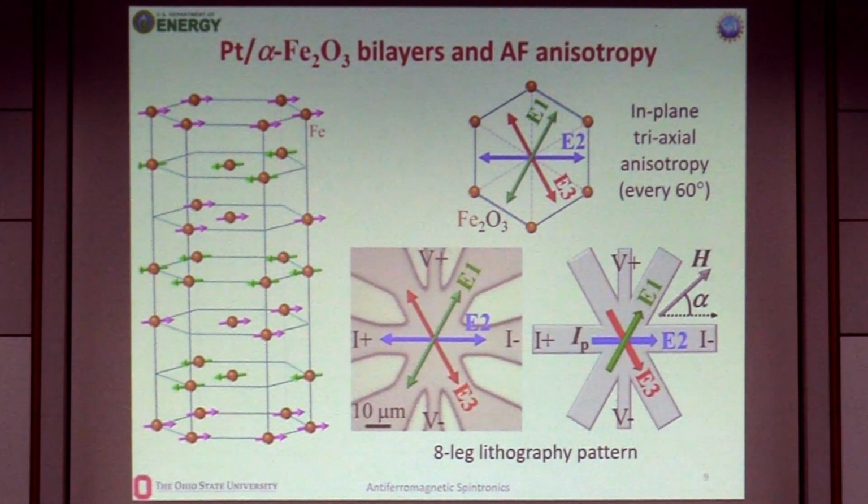We have an MBE chamber, so we have a RHEED, so my student used RHEED to align the crystal orientation and then make this pattern. This is an optical picture under an optical microscope, and that is a scale bar of 10 micron. I told them to use X-ray, which can also align this, but they like to use RHEED, but either way it works.